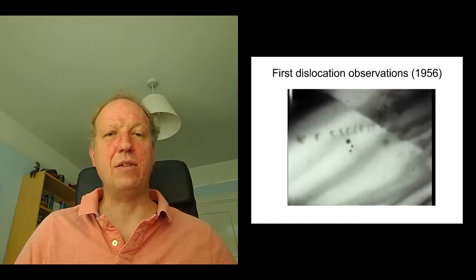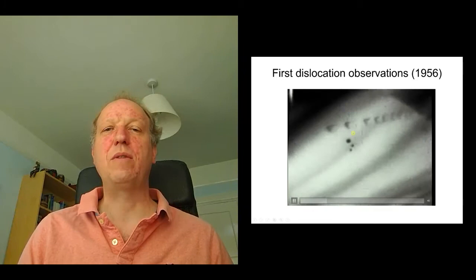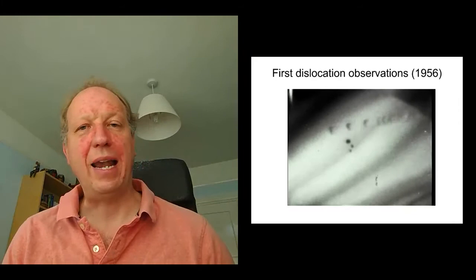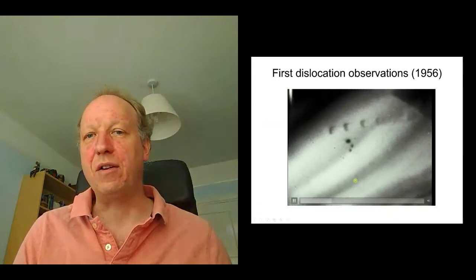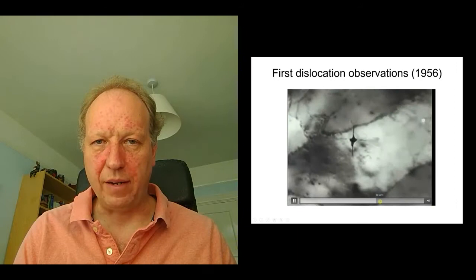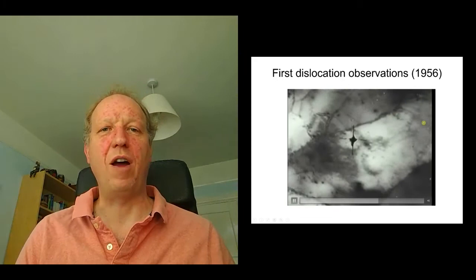And as the foil heats up under the electron beam, it starts to deflect a little bit. And you can see these dislocations all start to move. And so this was the first direct evidence of dislocations existing and that the motion of them allowed the deformation of metals. So this really was groundbreaking and confirmed really the existence of dislocations. Let's just scroll onto something. This is aluminium. Here we go. So there's a dislocation moving very rapidly through the material right there as the aluminium deforms.